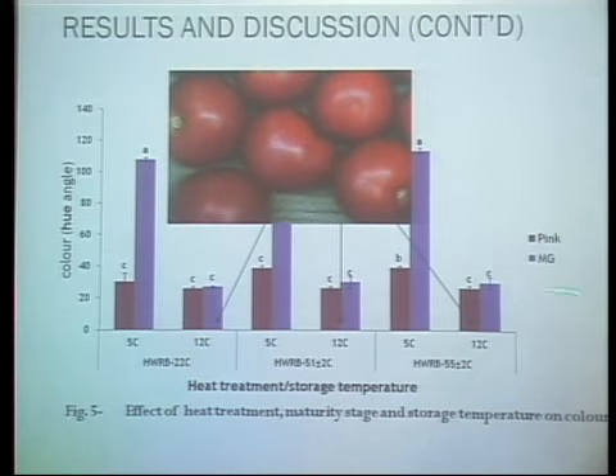And then for the color, we also noticed that the heat treatment, the maturity stage, and the storage temperature had significant effect on the color. There wasn't any interaction. And if you look at the chart here, you notice that at 5, there was significant inhibition of color, especially in the matured green, whereas for the pink, they ripened normally. And if you look at 12, both pink and then the matured green at this storage temperature ripened normally. But the inhibition of color was more pronounced in the matured green, especially at this temperature at 5 degrees Celsius.